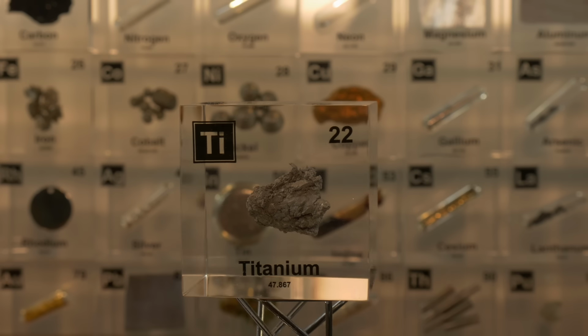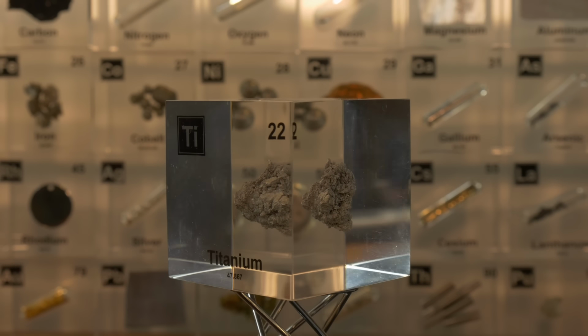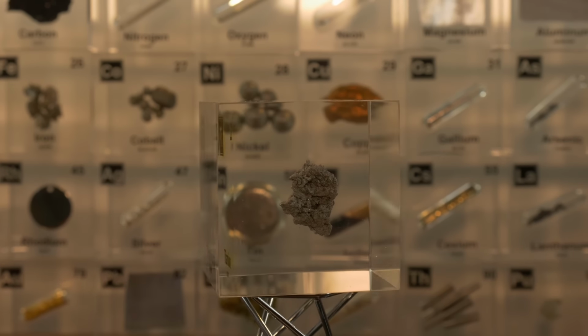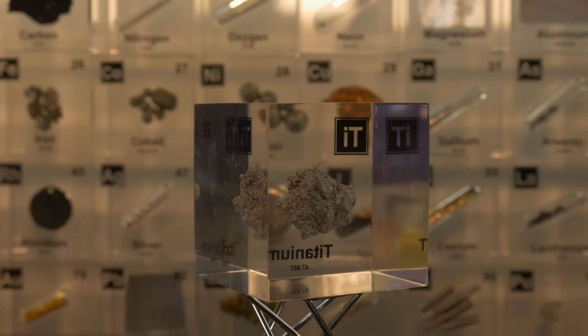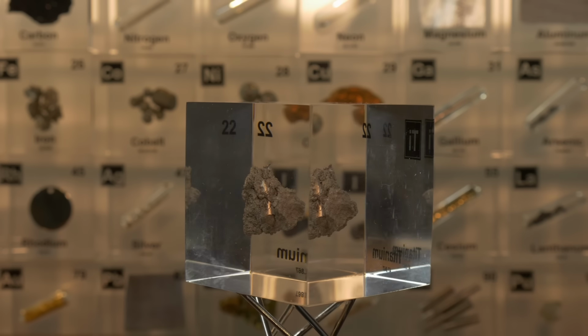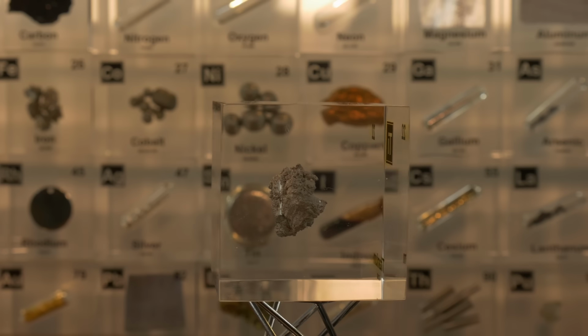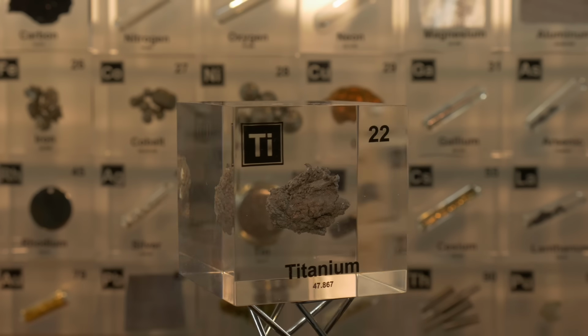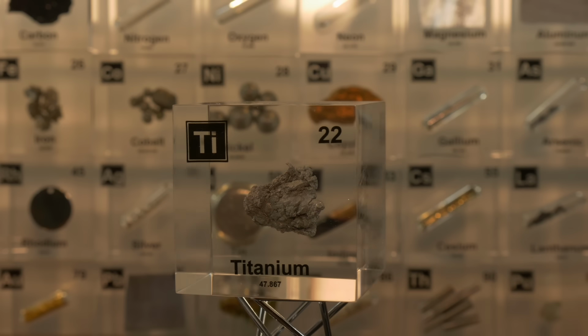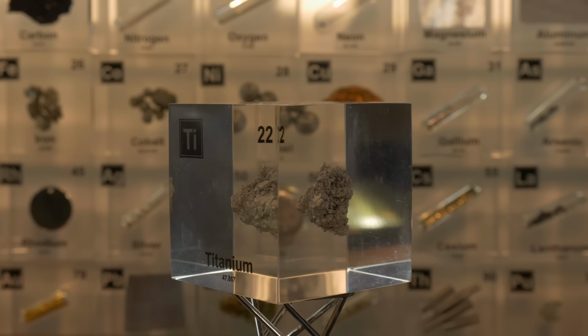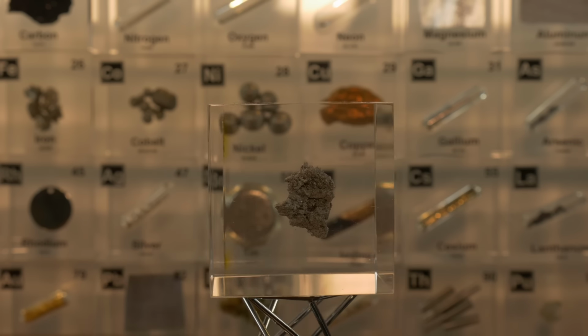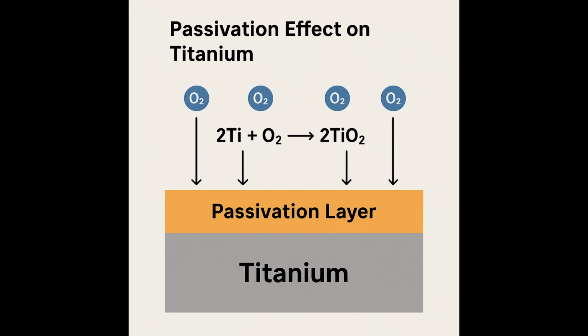Now, another example is hot concentrated acids. While titanium laughs at many acids when they're cool or dilute, hot concentrated strong acids like hydrochloric or sulfuric acid will corrode it. Heat and concentration tend to eventually eat through that protective oxide. Extremely alkaline or basic solutions at high temperatures can also attack titanium to some extent, though it's generally more resistant to alkali than to strong acid. Now, at room temperature, titanium is quite content and inert due to its oxide shield.